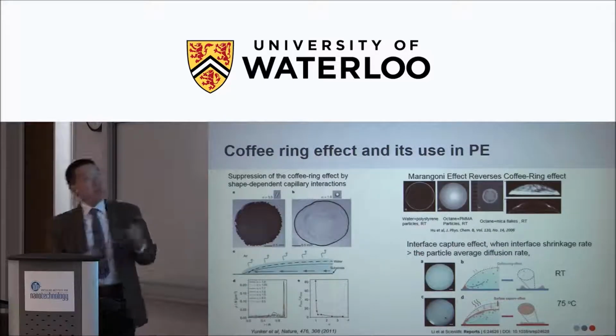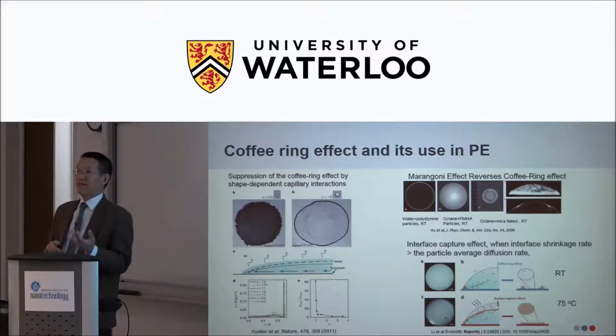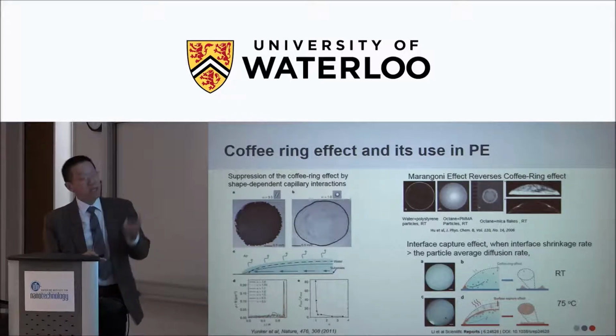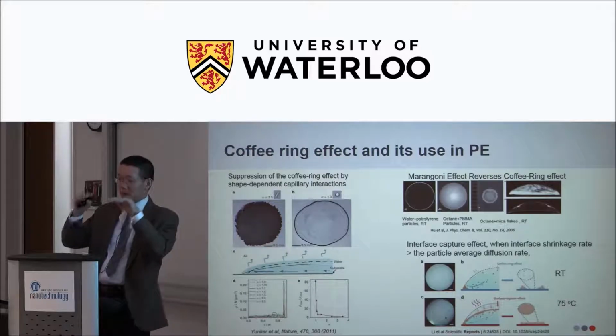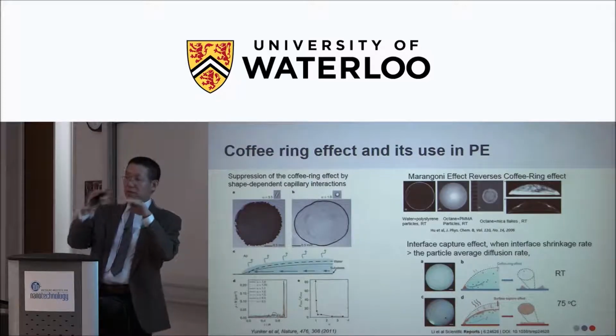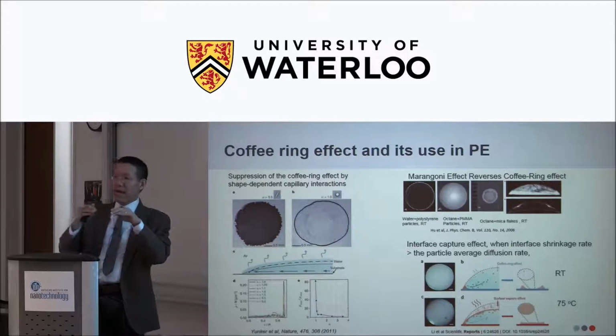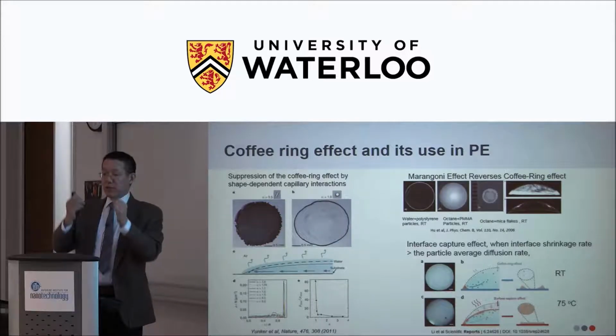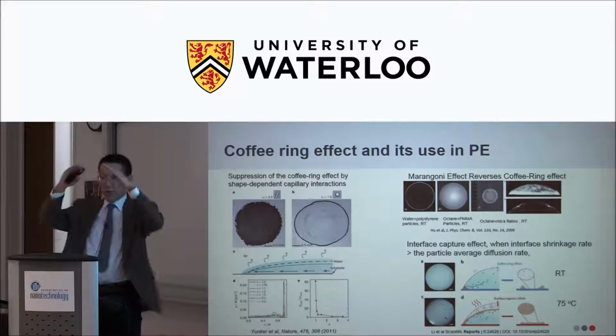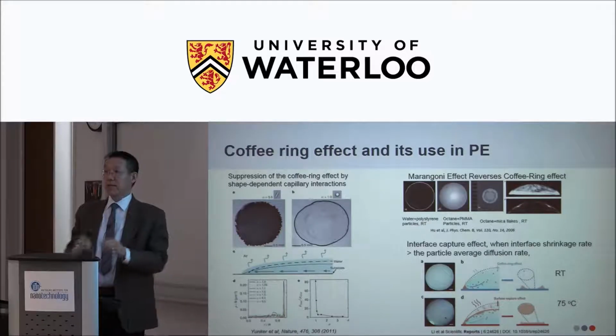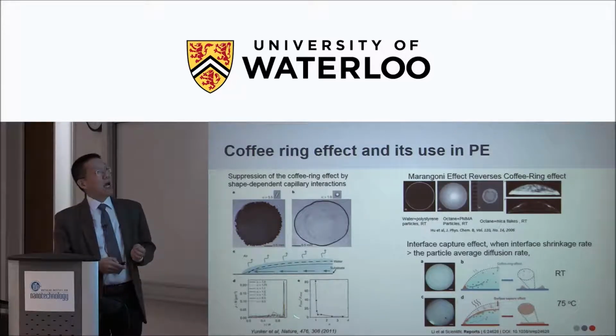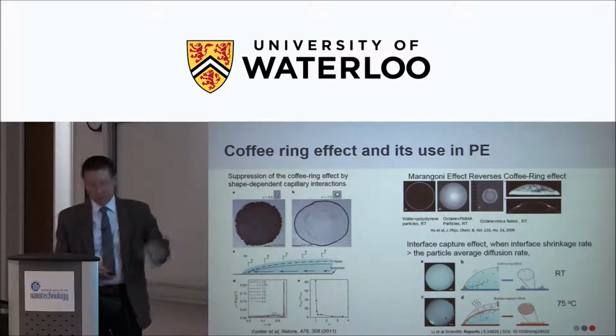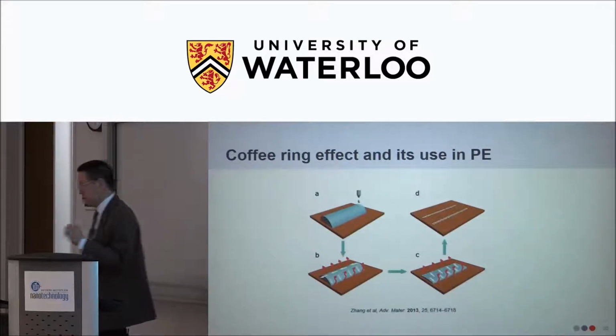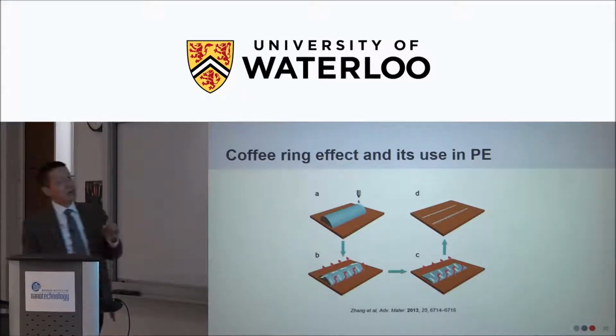But there's a way to control the drying process, right? You can either make these particles a different shape, so their mobility along the surface can be slowed down, or you increase the evaporation speed so that you can quickly evaporate the solvents, and the matter in the liquid will be deposited on the surface uniformly. So you can control that process. And there are a lot of papers about this.